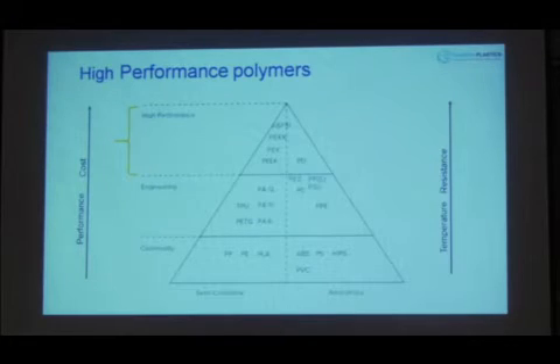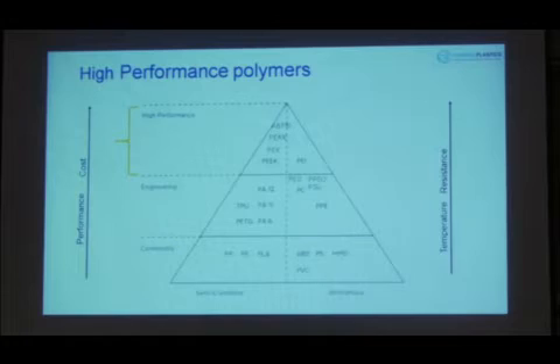So with unfilled material, it can withstand 240 to 260 degrees C, and when you add carbon fiber in that, it can go up to 300 or more than 300. So there is a PAEK group. So in that PEEK, then PEK, PEKK, and ABPBI. And in right hand side, it is polyetherimide, which is a transparent material. ABPBI is one of the fantastic materials.